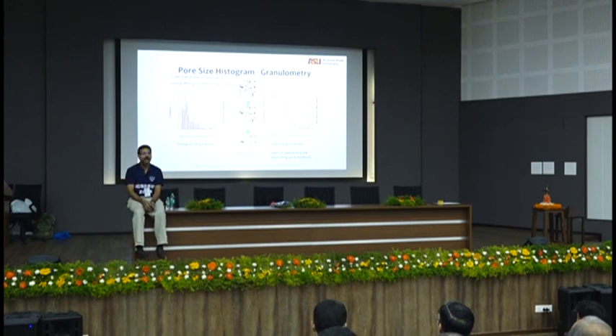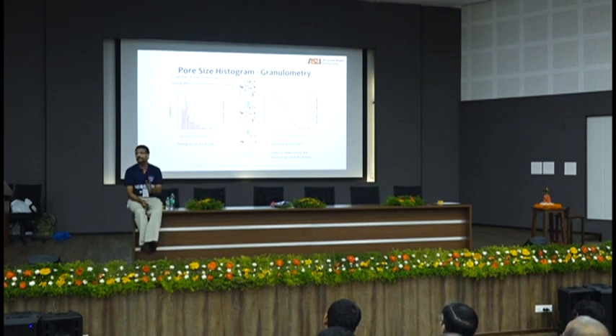as text files, ask it to do the granulometry, so write a subroutine for granulometry, ask it to do the granulometry on each of those images, ask it to spit out the results in each of those plots, you do a statistical analysis, you come up with the exact percolation threshold, percolation pore size in these structures. Very, very powerful characterization method, where if you want to understand what the pore structure and pore size are, if you don't have MIP, don't bother. If you can get a few images, you can work on it.